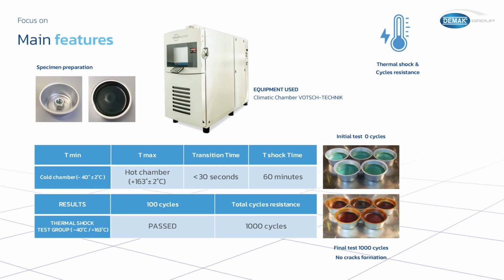We focus the attention on thermal shock. We have performed a thermal shock between -40 up to 163 degrees, so a very high jump of temperature, more than 200 degrees, with a passage between the cold and warm condition less than 30 seconds. We speak about 10, 15 seconds more. And thermal permanence at low and high temperature of 60 minutes.